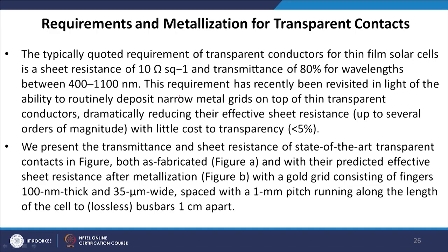Now, typically the requirement of transparent conductors for thin film solar cells is a sheet resistance of 10 ohm per square and transmittance of 80% for wavelengths between 400 to 1100 nanometer. This requirement has recently been revisited in light of the ability to routinely deposit narrow metal grids on top of the thin transparent conductors, dramatically reducing their effective sheet resistance by up to several orders of magnitude with little cost to transparency, less than 5%. We present the transmittance and sheet resistance of state-of-the-art transparent contacts in the next figure,